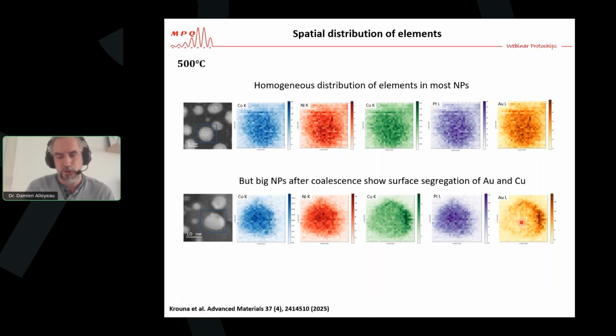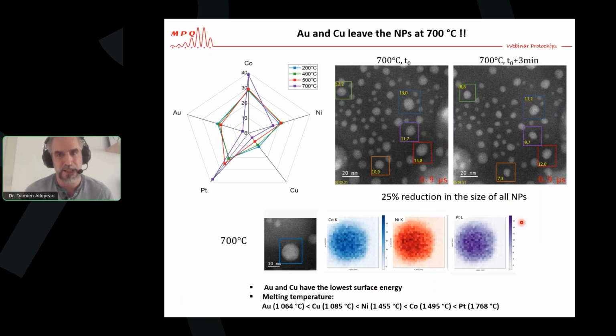Now, the most striking result of this experiment happened at 700 degrees. Just after reaching this temperature step, we observe a size decrease of the nanoparticles, a 25% reduction of the nanoparticle size. Here you see this on those images, and here on this diagram, you see that we completely lose the gold and the copper from the nanoparticles. So those two metals leave the nanoparticles and evaporate in the microscope.